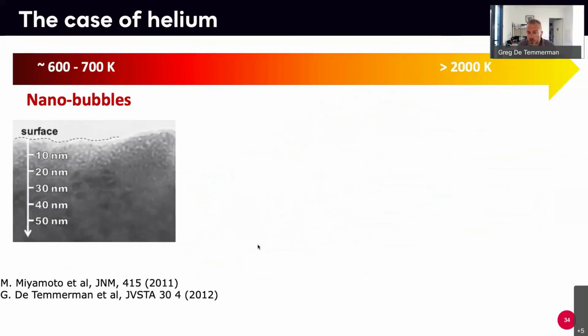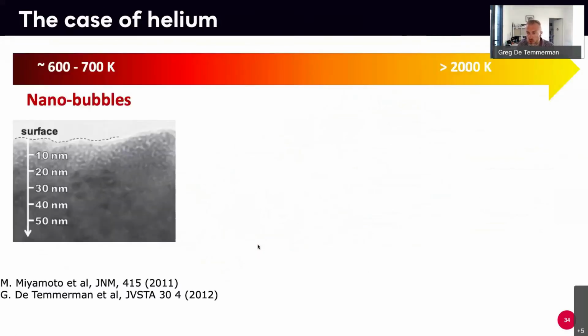And the funny one that I want to show you is helium. Helium is created by the fusion reaction. You have bombardment of helium ions onto your surfaces. And what is fascinating is that in principle, helium is not soluble in metals, at least in tungsten. The solubility limit is basically 0.